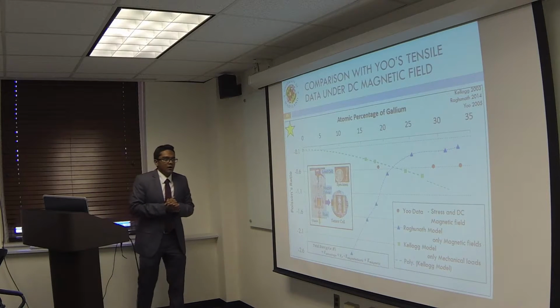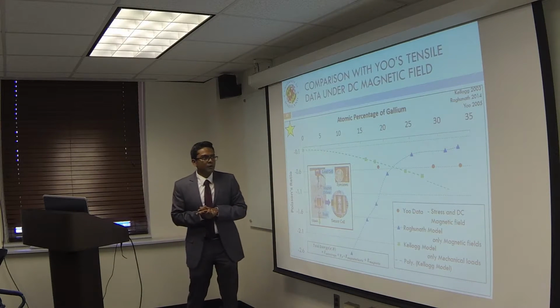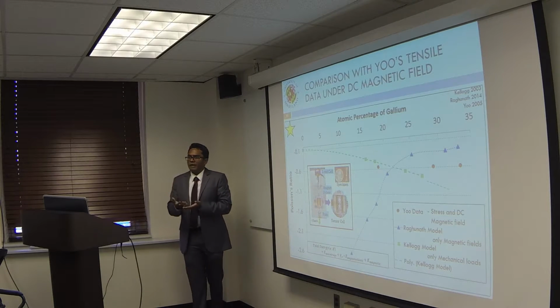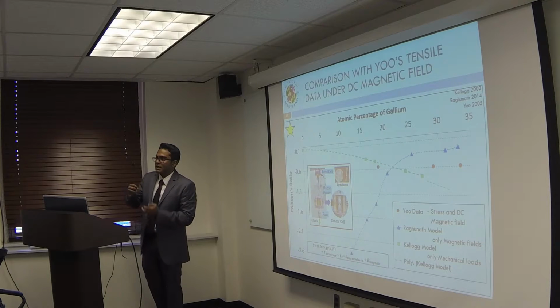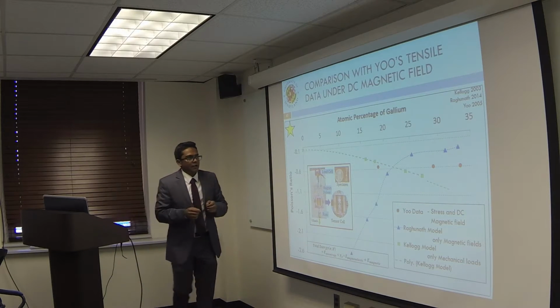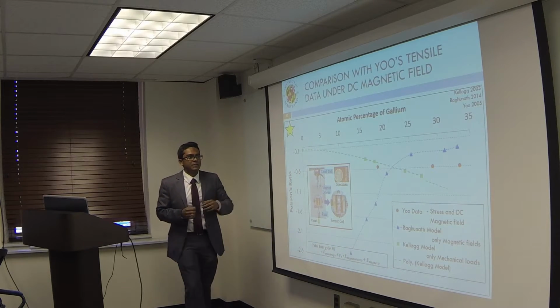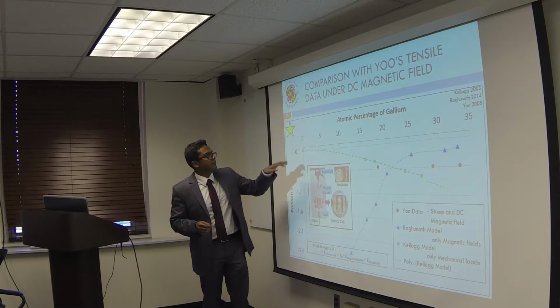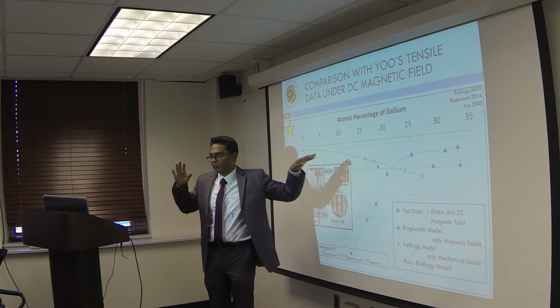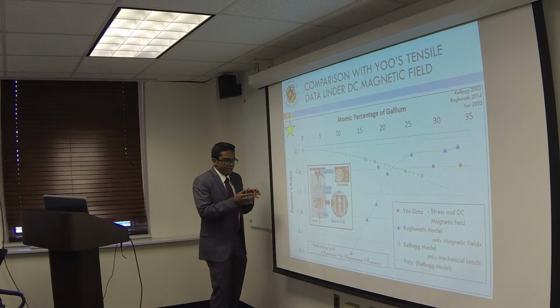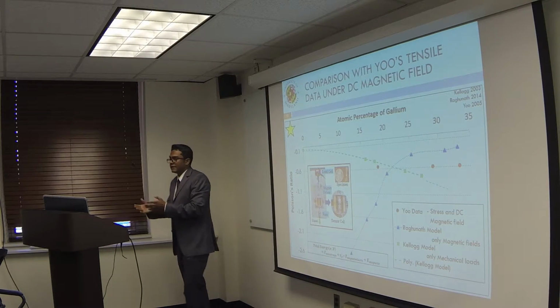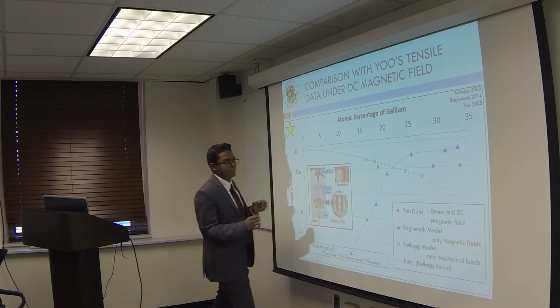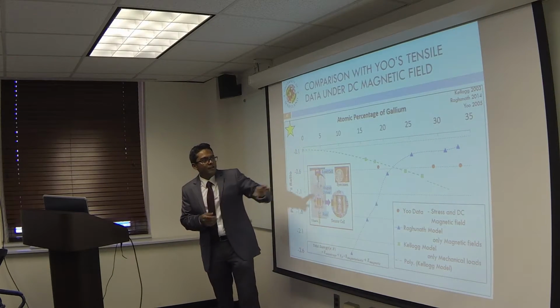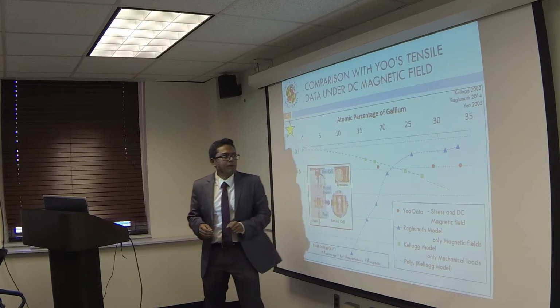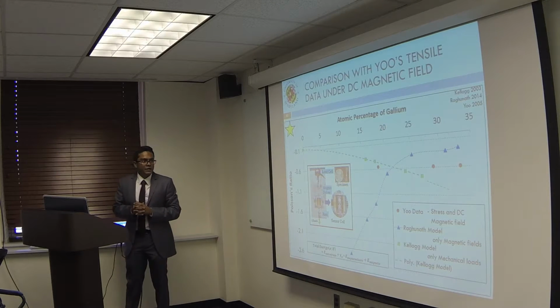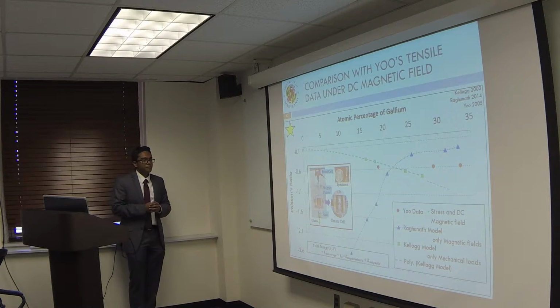So interestingly, a previous postdoc from our group, Yoo, measured the values of Poisson's ratio under applied tensile loads in the presence of a DC magnetic field. The red dots show the values that he got experimentally. If I compare this with the values that Rick Kellogg got under applied tensile loads under zero magnetic fields, and the values that I get with applied magnetic fields and zero tensile loads, we find a very interesting phenomenon. The values of Dr. Yoo are right between the values that I predicted for zero applied tensile loads and the values that Rick Kellogg had predicted.